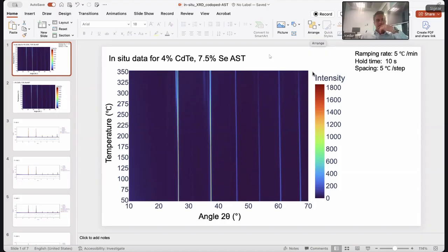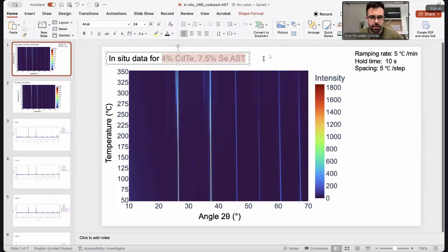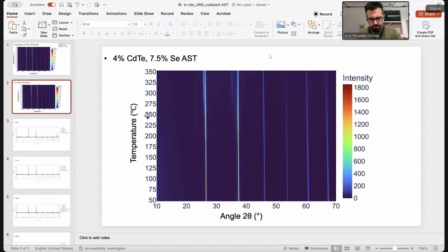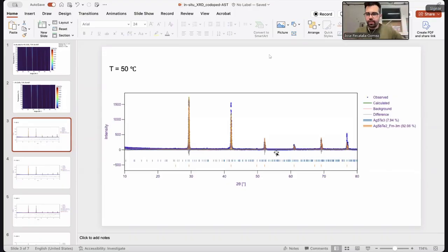Oh, phase viewer all the way. Yeah, not really actually. This is really interesting. I just got this data yesterday, so I've only spent very little time analyzing it, but basically I can now do in situ XRD here in nitrogen, and the results are fantastic, quite frankly. I tried with this sample because I had it handy and it's not so important. So basically, it starts with, as we know, silver antimony telluride. Then it goes, and we have some silver telluride as well.